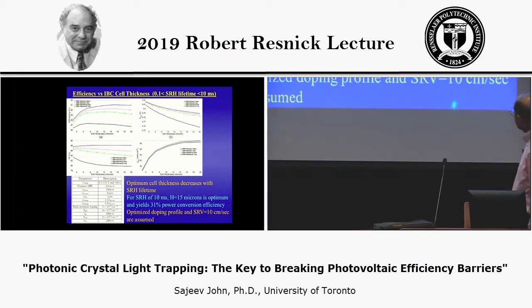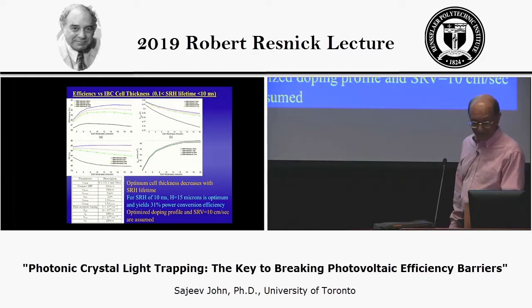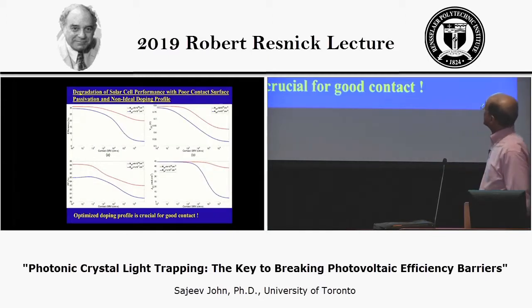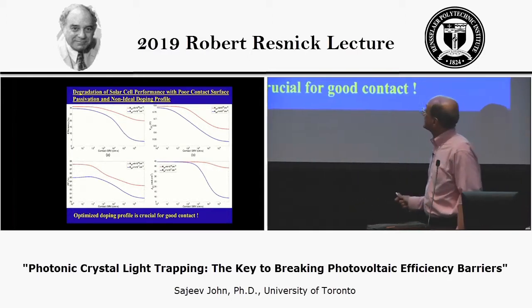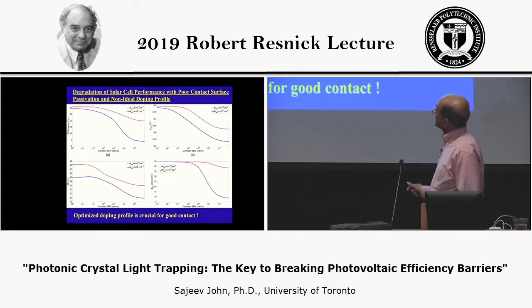And so this is what we think combining state-of-the-art surface and contact passivation, state-of-the-art bulk passivation and reduction of defects, creating this 10 millisecond carrier lifetime, is possible with a very thin and flexible 15 micron thick silicon structure. Now I'll add one caveat to that: surface passivation really is very important. If you were to make the surface recombination velocity much greater than 100 centimeters per second, you can see that the efficiency would drop rather rapidly.